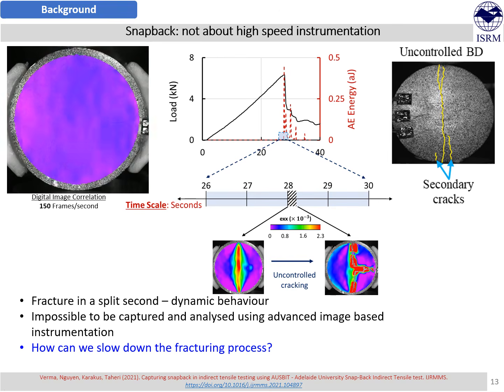Now, with the high speed camera, we tried different frames per second with different image capturing speeds. We started with 5 frames per second and we extended it to 150 frames per second. However, with all these variations in frames per second, we realized that the local scale dynamic is so dominant that it couldn't allow us to quantify or capture the local scale behavior in quantitative terms to link it with material property. And that made us realize that snapback is not about high speed instrumentation, but it is about the local scale dynamics. If we could control this local scale dynamics associated with disk cracking, we could enable an efficient application of digital image correlation or high speed instrumentation.